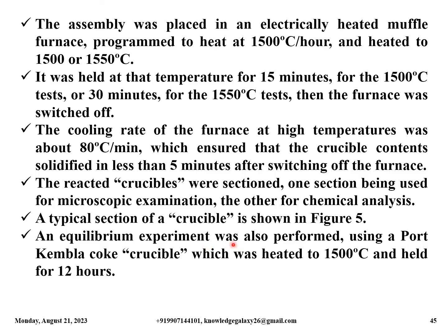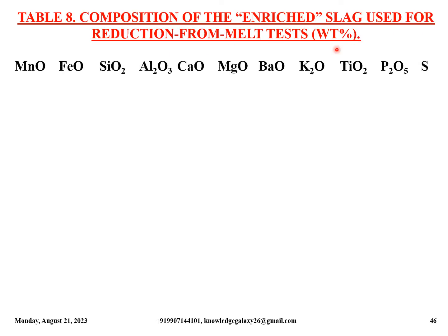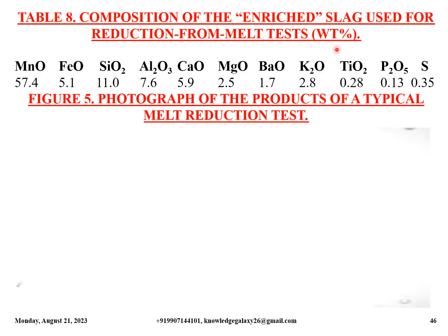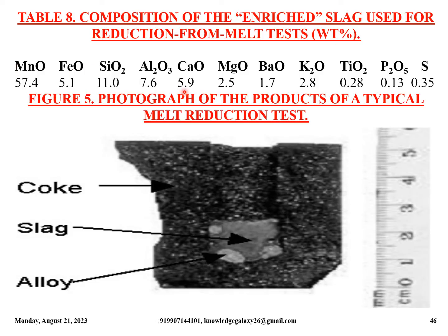An equilibrium experiment was also performed using a Port Kembla coke crucible which was heated to 1500 degrees Celsius and held for 12 hours. So this is the table which shows the composition of the enriched slag used for reduction from melt tests in weight percentage. So this is the table with all the figures, and this is the photograph of the products of a typical melt reduction test. So you can pause the video and observe this very carefully.